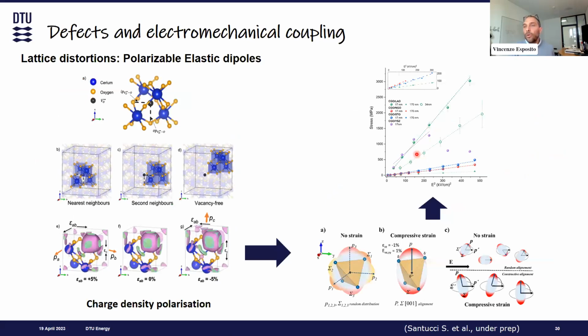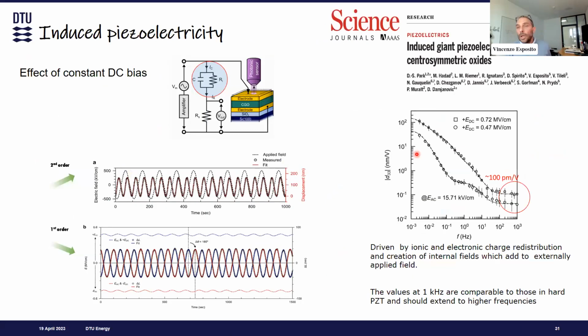And this seems to also confirm some of our results, especially those related to strain. And the DFT calculation tends to agree with this hypothesis. But a take-home message is also that as soon as we can get high distortion in the system, we can actually get a nice electromechanical response. This has been done in another publication in Science in collaboration with the EPFL group, where we show that if we can strain the material by applying a DC signal and overlapping an AC signal on it, we can get some kind of linear response, as typical of a piezoelectric material.